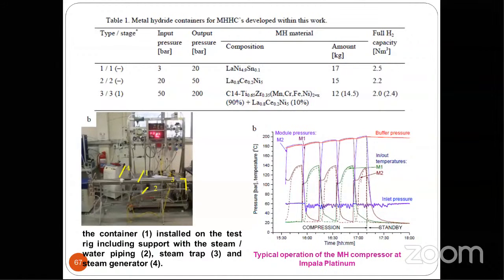So by using this low grade heat, you can compress the hydrogen without using a mechanical compressor. We have tested this compressor, and it achieved up to 200 bar. So this system we can use for hydrogen refueling stations. We have to generate hydrogen infrastructure for hydrogen-based transport vehicles.